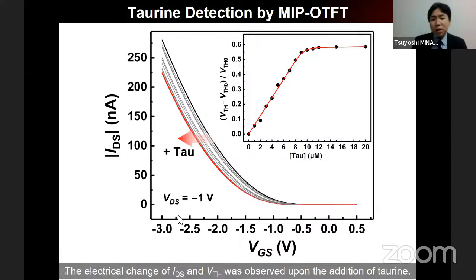This is a typical example of the transistor characteristics, the gate voltage and drain current. As you can see, when we increase the concentration of taurine, we can see a shift of the transistor characteristics. Here is the relationship between taurine concentration and threshold voltage change. We clearly see a nice saturation curve, and at the lower end of the concentration it is a linear line.